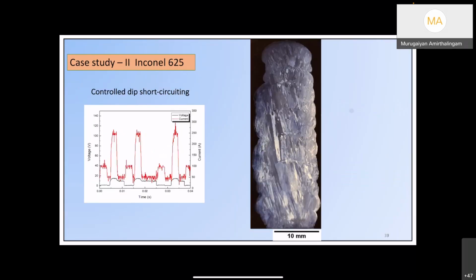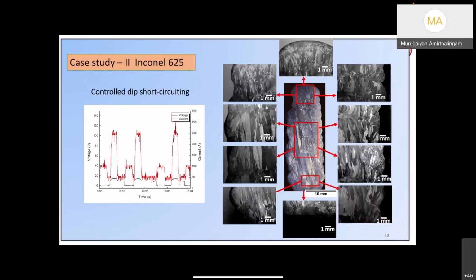And if you change the current voltage waveform, despite keeping the same arc energy heat input, the microstructure may not be directionally solidified. So what we need to understand here is that the current voltage waveform and the metal transfer that we carry out can significantly influence the microstructure evolution. Good. So that's what I show over here. If the current voltage waveforms are changed, the microstructure can differ significantly, by the fundamental principles that I described.